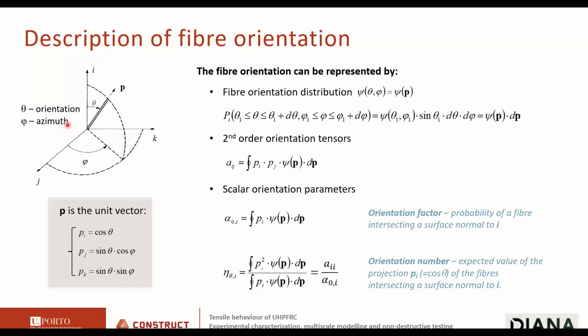The azimuth is the other angle that you need to use to define completely the fiber orientation state. So P here is the unit vector in the direction of the fiber, okay? The most complex and most general methodology to describe the fiber orientation is using a fiber orientation distribution, which has to have some properties that we will discuss, and use some stereological principles to get the information that we need. A simpler way is to use second-order orientation tensors, which can also be helpful, but even simpler is using scalar orientation parameters. And we will focus a lot on this one.